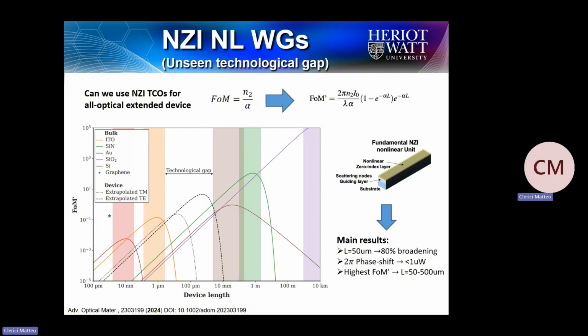A very straightforward approach is provided by this optical interconnect, where we have a low loss single mode channel, then we have on top a spacer, and then on top a thin film of our highly nonlinear material. And so you have the mode that is propagating in this waveguide that is evanescently coupled with this thin layer of, in this case, ITO. And so we can moderate the losses because the field is confined in just a tiny fraction within the ITO. But we also moderate the nonlinearity. So it's a trade-off.